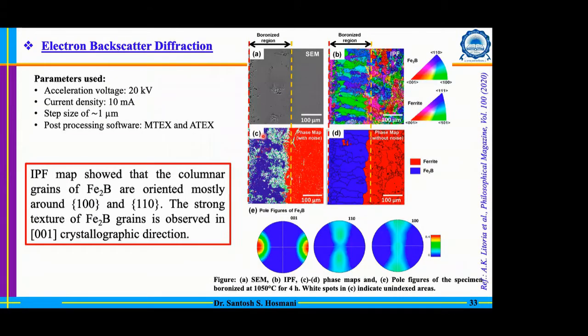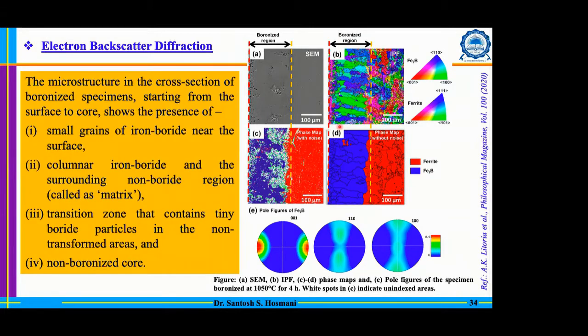Now the EBSD, that is electron backscatter diffraction, helps us understand the orientation of phases as well as which phases are forming there. We have confirmed that you have the stacking of the 100 and 110 planes in the 001 crystallographic direction. Apart from that, near the surface you can see very fine grains, and subsequently columnar grains are visible. That means in the boride region you have two important regions, the small grains and the columnar grains, and then subsequently a transition zone, and then the core.